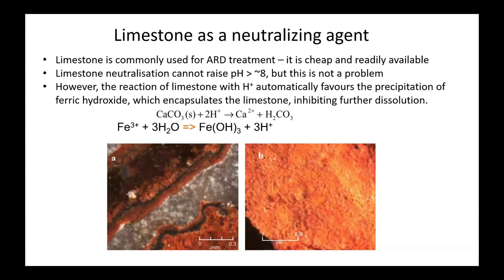And the reason for it is you can see calcium carbonate reacts with H+ to form calcium and at low pHs carbonic acid. When Fe3+ precipitates to ferric hydroxide, it releases acidity. So if you use up H+ with the top reaction, you force the bottom reaction to go even harder to release H+ that could be used up by the calcium carbonate. And this means that basically armouring of the limestone by ferric hydroxide is actually impossible to stop, but you can minimise it. At the bottom on the right, we can just see the surface of a limestone gravel covered in ferric hydroxide, and the left is a cross-section through it. The grey in the middle is the limestone, and you can see the ferric hydroxide has formed this layer coating it. Next slide.